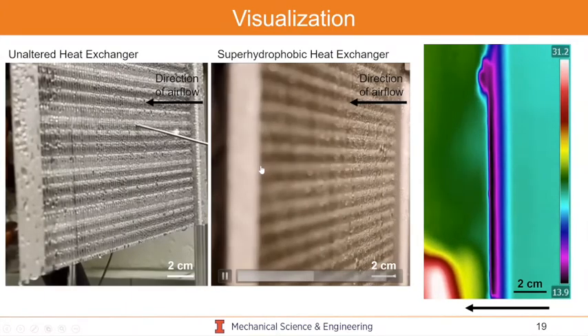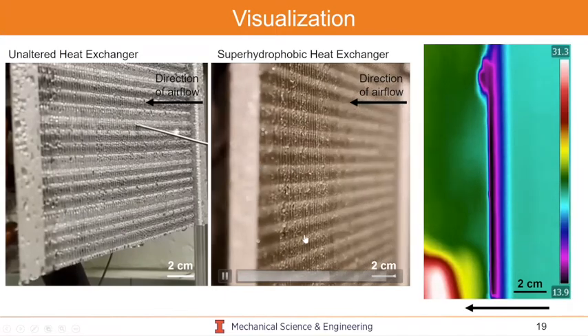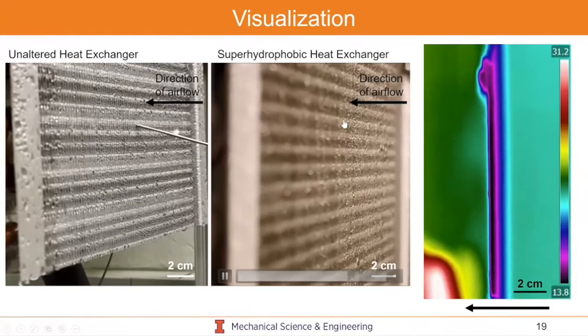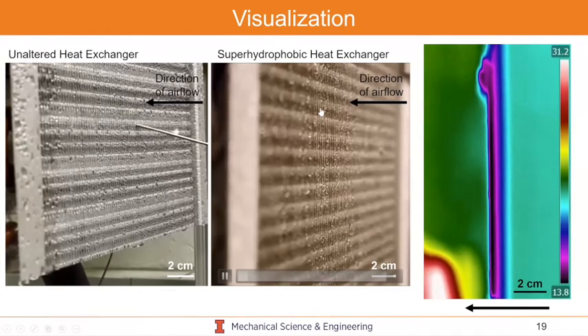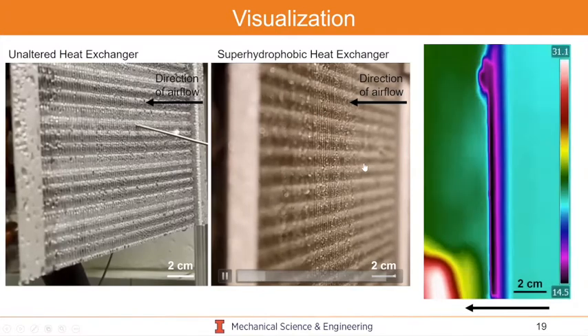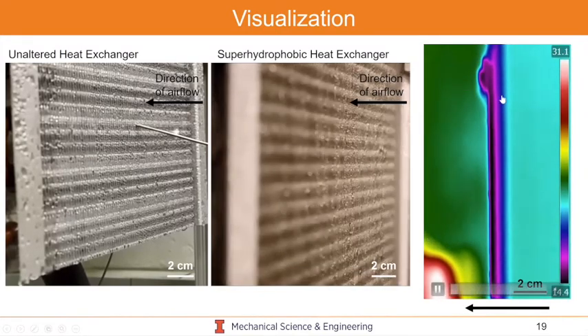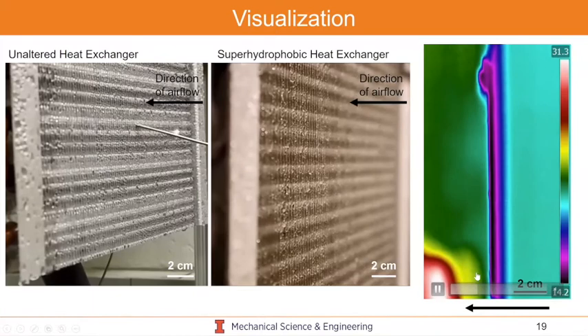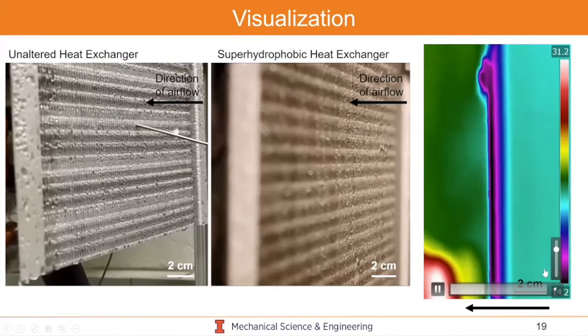But on a super hydrophobic heat exchanger, you could actually see here that in some instances, you could see droplets jumping out of plane into the wind. And so here, droplets are much smaller, and they actually depart from the surface through this droplet jumping mechanism. And this is more clearly seen here on this infrared image, where you could see that, even though your flow of air in this infrared image is from right to left, you're actually seeing droplets eject